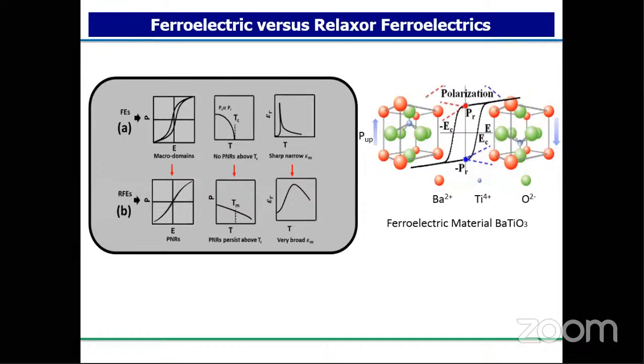So what causes the relaxor ferroelectric nature? When you increase charge imbalance or have different ions in a material, they destroy long range ferroelectric order and induce some small nano region ferroelectricity. Those regions we call nanopolar regions or polar nano regions. That is what the term PNR represents. In conventional ferroelectric materials, we have macro domains. When you come to relaxor ferroelectric materials, we have polar nano regions. These polar nano regions induce the relaxor nature in a conventional ferroelectric material. You can create that by controlling the grain size or by inducing different types of ions or atoms in the material, so that some charge imbalance takes place and they destroy the long range ferroelectric order.